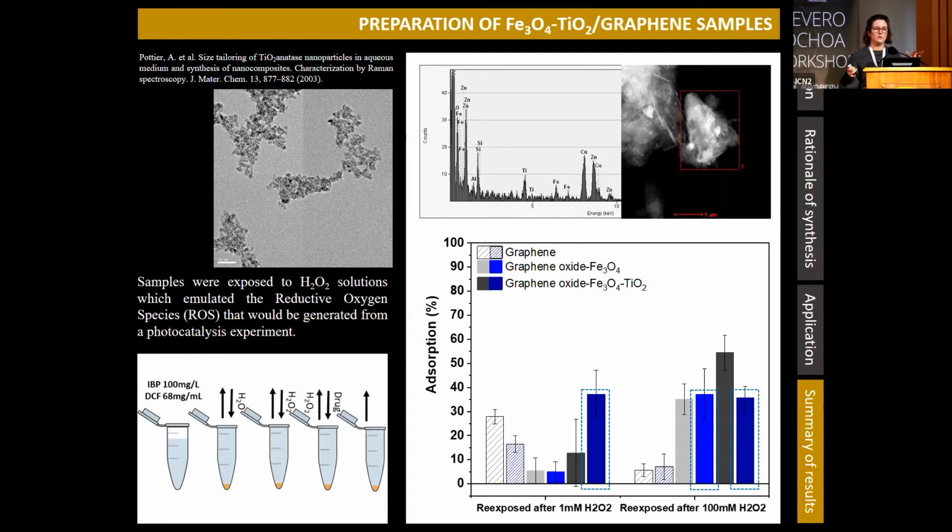This is most probably because we are going through a Fenton-like reaction here. In the case of ibuprofen, we see that it didn't work when we had a lower amount of peroxide, but it did when it was higher. It's most probably because if you remember, we had these temporary products that are in equilibrium. So probably with the higher amount of peroxide, we got to break this equilibrium and displace the reaction.